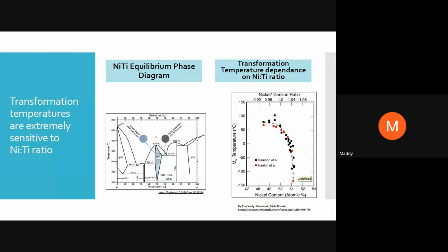You can control things. Whereas if you look at the titanium-rich side, it's pretty much straight. Like, there is no slope here. So on the titanium-rich side, you do have Ti2Ni precipitates, but that's not of much use in terms of controlling the functionalities, I would say. So these are a couple of things that I thought I should share as far as the alloy system is concerned. Next slide, please.